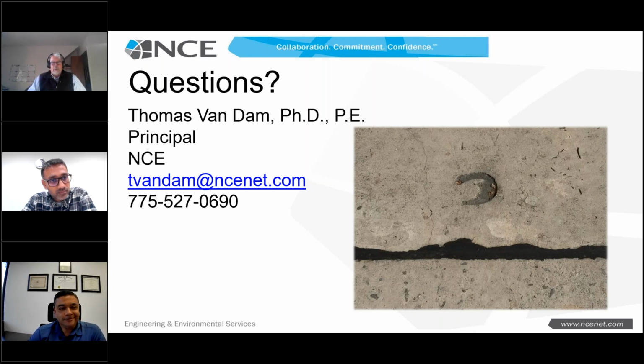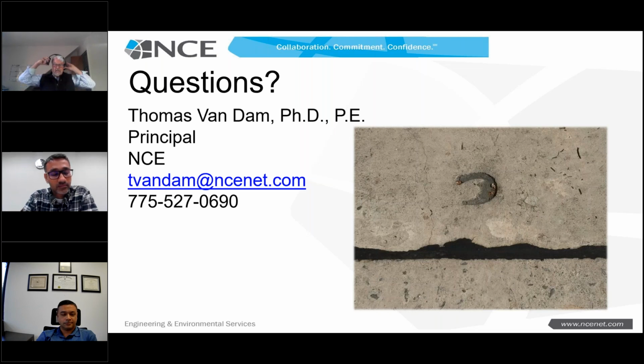So will a sequestration, in other words, carbonation of concrete, will it cause what? Corrosion. And that is an exceptionally good question, and one of which it absolutely could. We rely on the high alkali environment of concrete to protect embedded steel from corrosion through the formation of a passivation layer. And what happens is if that alkalinity drops, which would happen in carbonation, the passivity layer breaks down and corrosion can ensue.